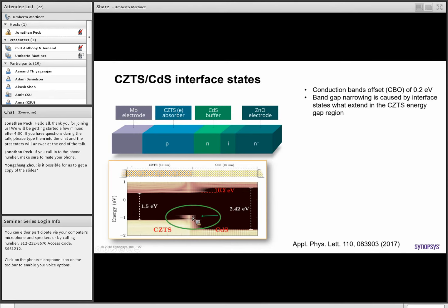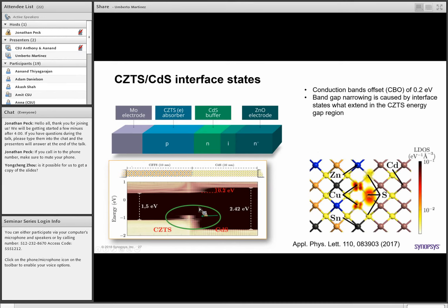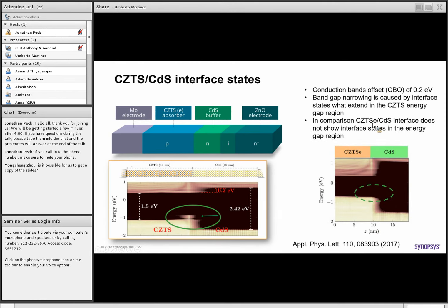However, we also find that there is some band narrowing close to the interface, and this is due to these localized gap states which extend into the gap region. We can of course look into more detail at these states, and if we do a charge analysis and zoom in on the interface, you can see that these states in real space belong to the copper atom and the sulfur atom. So this is a fingerprint of this specific interface. And in fact, if we compare with a selenium-terminated interface, so we take another material, we immediately see that these interface states don't show.